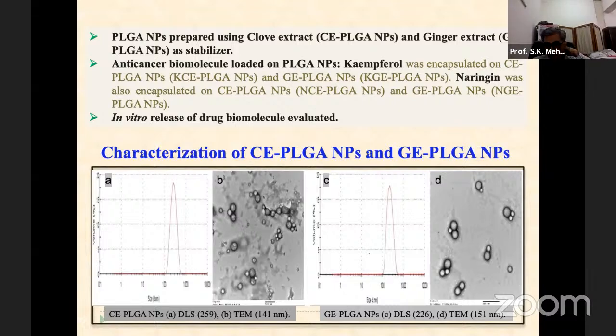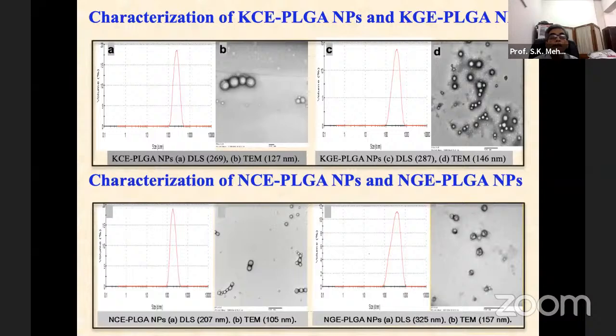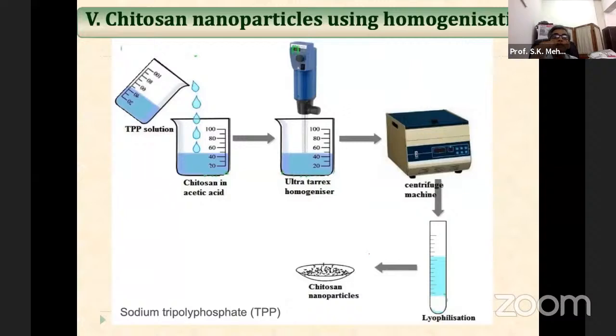So a lot of work has been done on this, and two types of these drugs were encapsulated, and we saw their release also, and their pictures you can see. The particle size 141 nanometer, 151 nanometer, and then characterization of both KCE and NCE was done. And again, the particle size was found. It is between 100 to 200 nanometer, which is acceptable from a biological point of view.